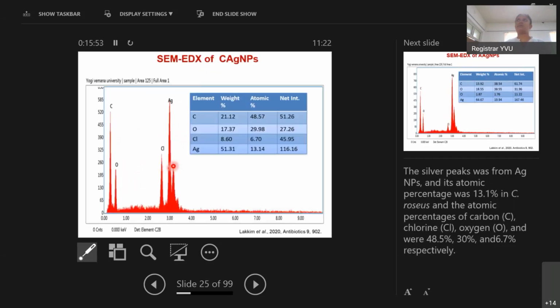These are the same EDAX of the Catharanthus roseus silver nanoparticles. This sharp peak represents the presence of element silver. The elements carbon, oxygen, chlorine, and silver are present. The weight percentage of silver is more compared to the other metals: 51.31, the atomic percent 13.14, and net intensity is 116.16.